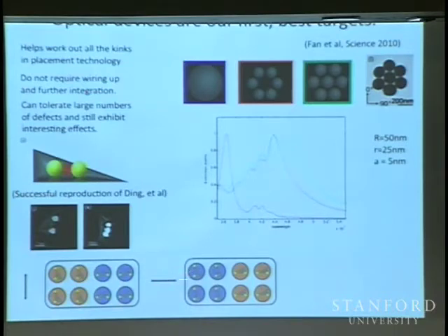If we had white light polarized in this direction, then we would see these guys as red and these guys as blue. So we can change the polarization, and based on the orientation in which we've placed these metal dipoles using DNA structures, we should be able to get different colors. That's been done before with lithography. People have placed little metal dipoles, little metal disks, and based on the orientation of the disk, they can get a different scattering spectrum depending on the polarization. That was all done by lithography in the early 2000s.